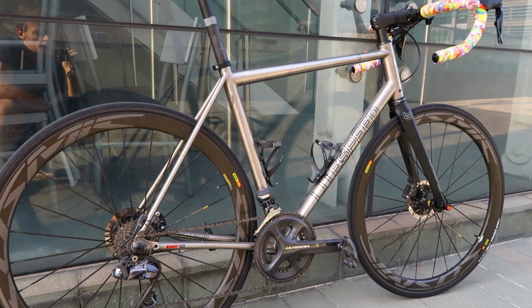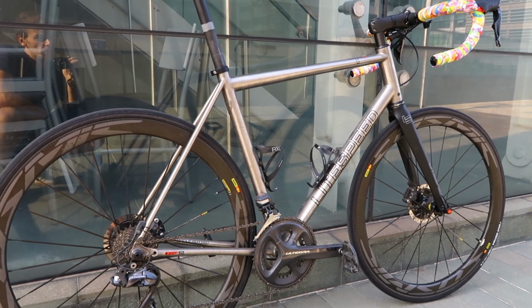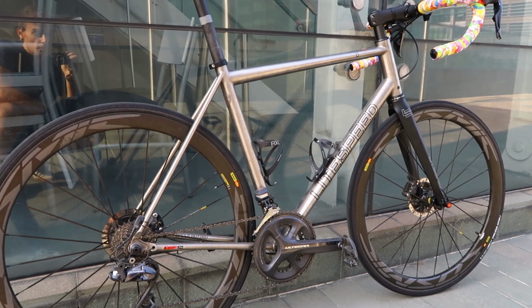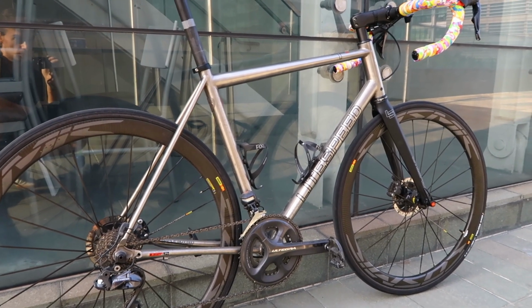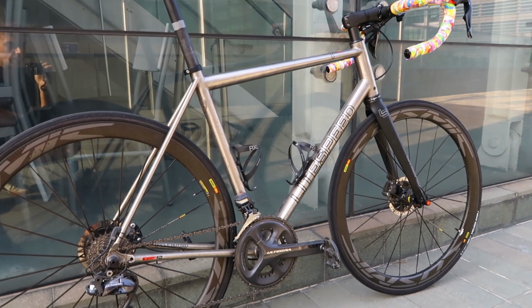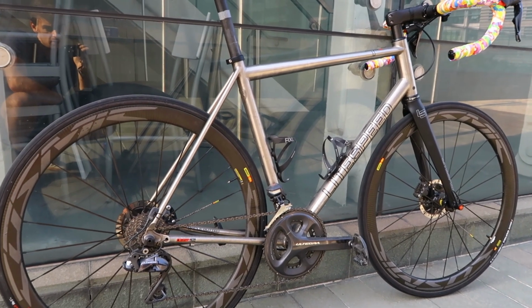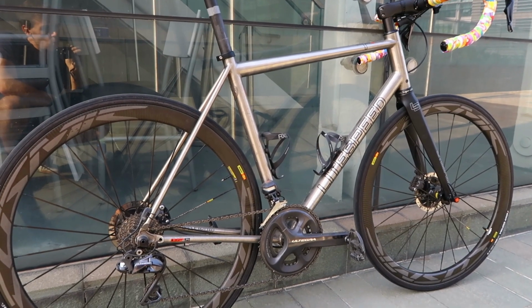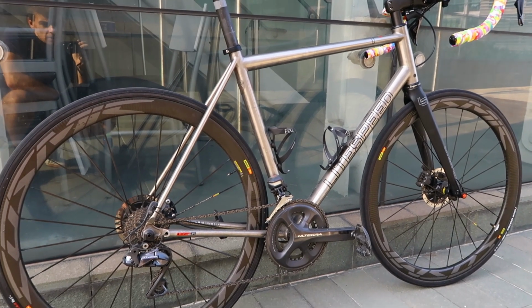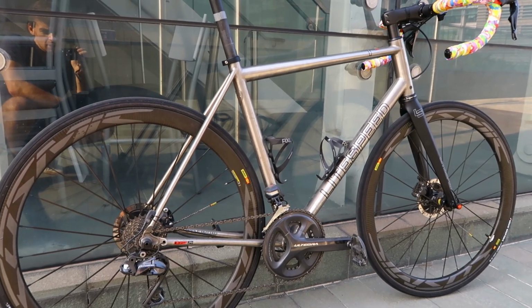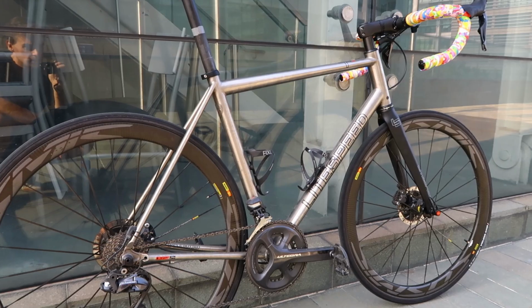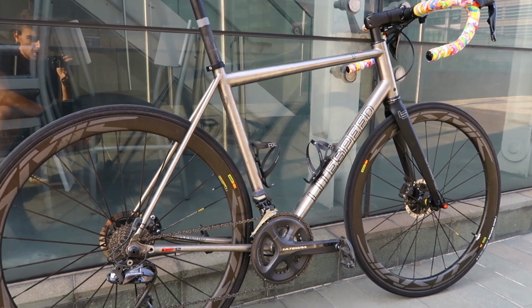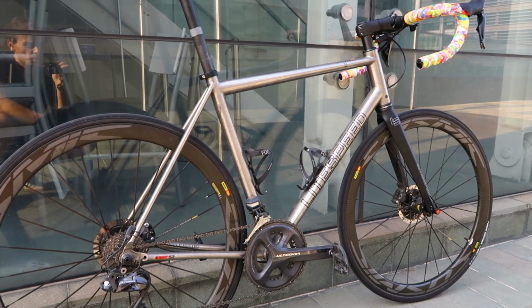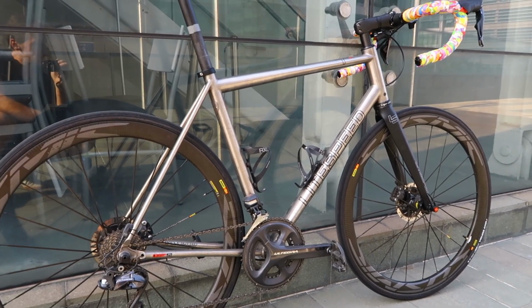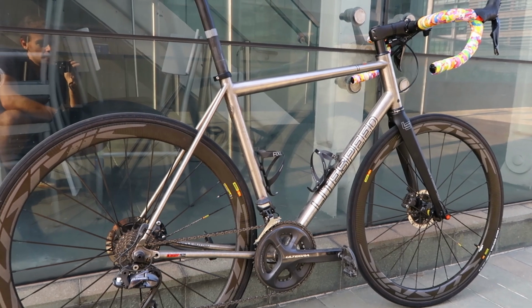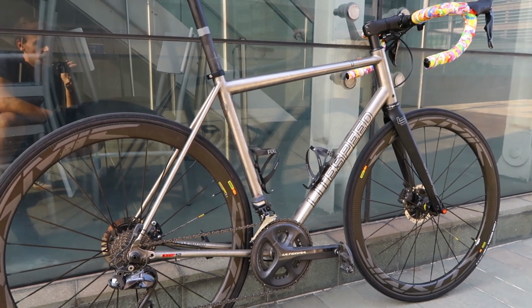and you had one titanium frame and one aluminium frame, and both bikes weighed 8.5 kilos, I can tell you the stiffness, so ride quality, compliance, flex, comfort, or stiffness, pedaling stiffness, blah, blah, blah, will be almost exactly the same, because the specific modulus of aluminium and titanium are almost the same. It's about 25, 26. So titanium is stiffer, but it's heavier. Aluminium is less stiff, around 72 gigapascals, but it's much lighter. It's got a lower density. But those two figures divided by each other give you the same figure, about 25, 26 for aluminium and titanium. So if you have two frames that weigh the same, they are going to be the same stiffness, whether it's aluminium or titanium, more or less.